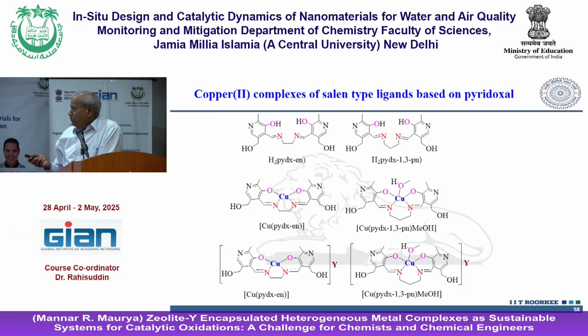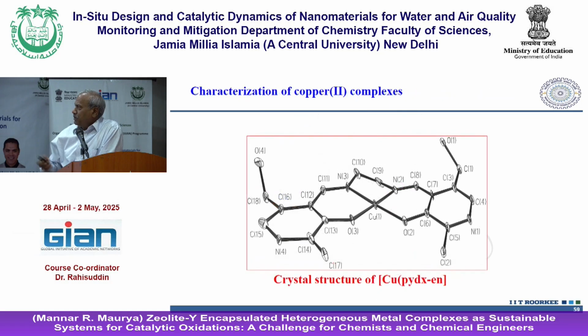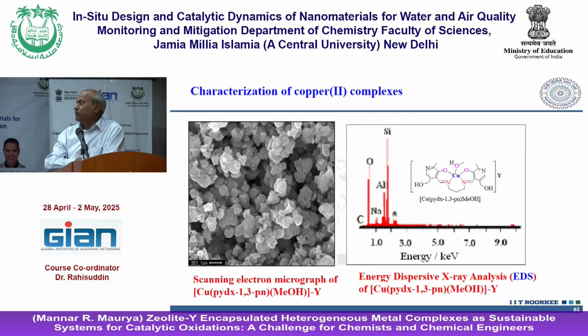Copper compounds have also been prepared, and then after characterization of these compounds, here we have tried to do EDX, now available. Okay, and in EDX you will see that one copper peak can be seen there, a small peak is there, so that gives the idea. But as I mentioned, you cannot see too much. Sometimes when you are lucky you will see the small peak, but because it's encapsulated inside, you cannot see really well, but that gives some idea.